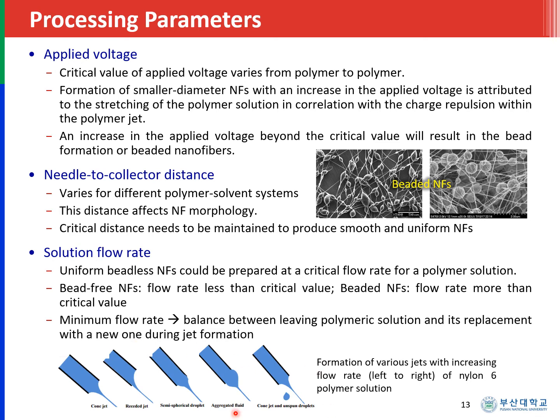As shown in this figure is the formation of various jets with increasing flow rate of nylon 6 polymer solution. The leftmost image gives a very good geometry of the jet, a cone jet, and then this rightmost image also has a cone jet, but it has unspun droplets. So definitely this type of jet would lead to poor quality nanofibers, and it will adversely affect the properties of your nanofibers.